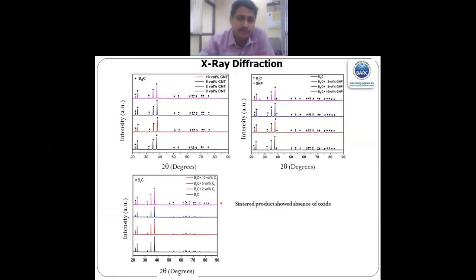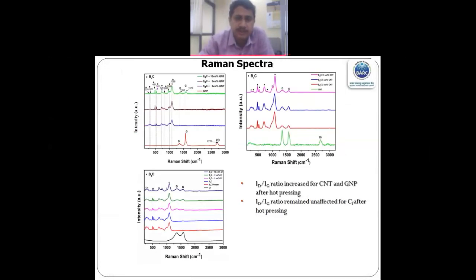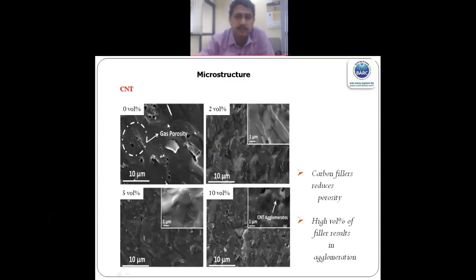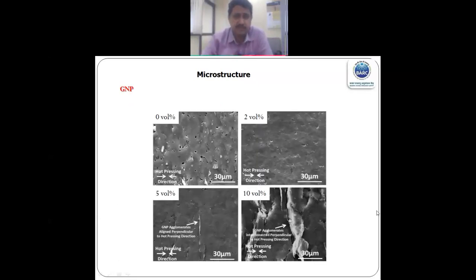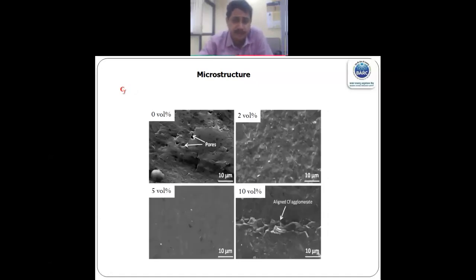This is the XRD, which shows there is no boron oxide remaining. And this is the typical Raman spectra, which tells us the presence of both carbon materials and boron carbide. This is a microstructure. This is very important. If I increase the carbon nanotube volume percentage, what happens? Initially with 0 volume percent, some porosity is there. The porosity gets reduced, and finally with very high volume percent we get agglomerates. The same thing happens with graphene nanoplatelet as well, and carbon fiber as well.